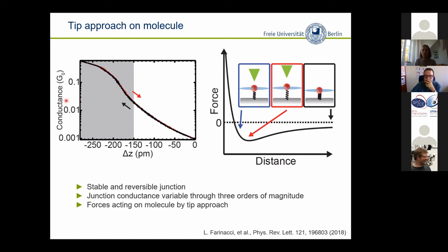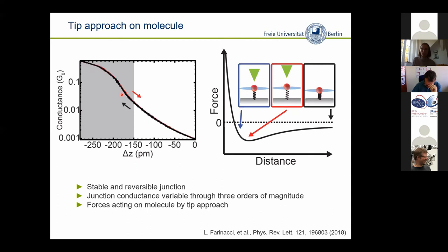Here is what we do in the experiment: we can have the STM tip far away for non-perturbative measurement, but we can also come closer. By coming closer, we measure the conductance — an exponential increase which eventually levels off, typically associated with contact formation. Nicely, in this system you can approach with the STM tip, find a certain increase in conductance, and go back and it falls on exactly the same line — highly reproducible. So we can also stop at any point of this position and start to measure the YSR states at different conductances.